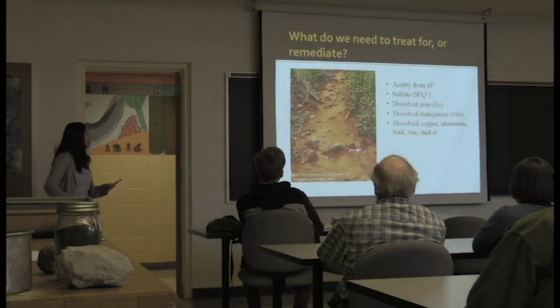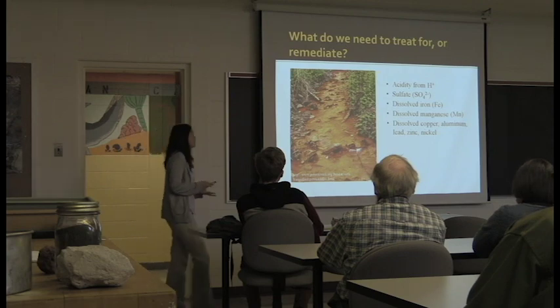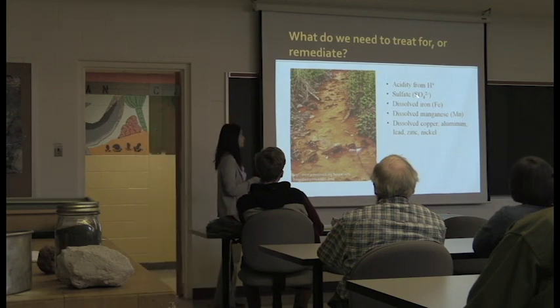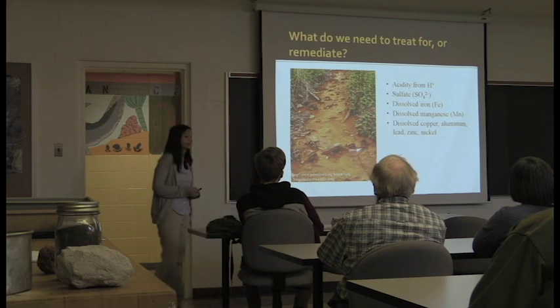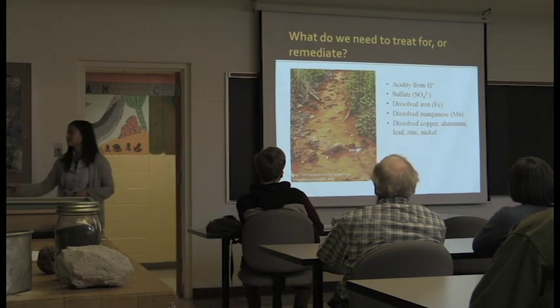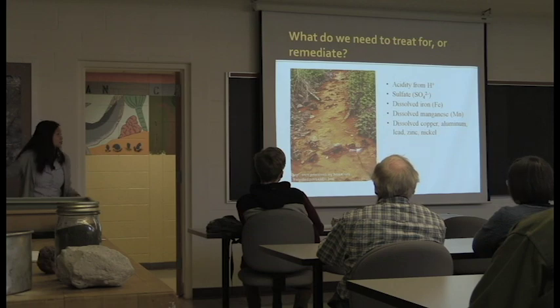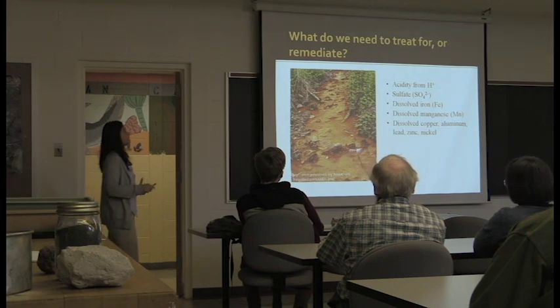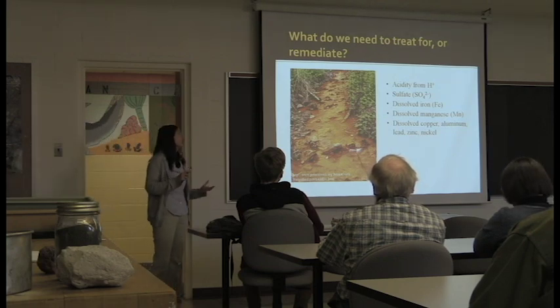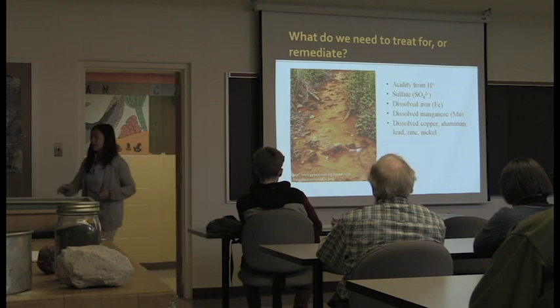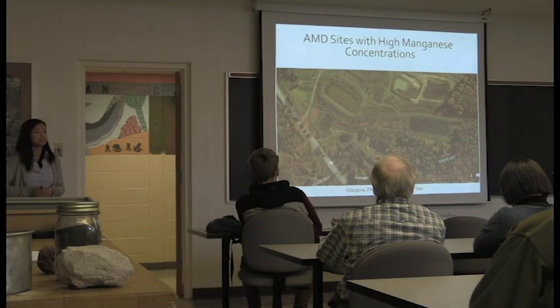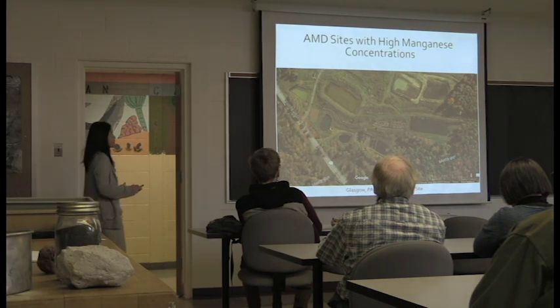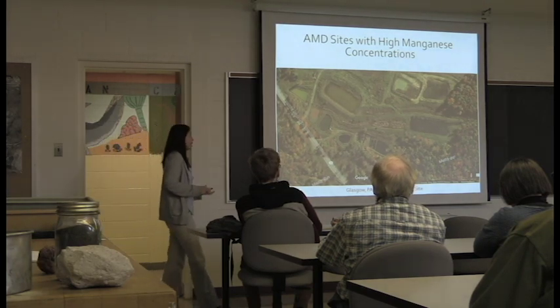So far, if we think about what we were trying to treat, we've treated a little bit for acidity, we've treated for sulfate, and we've treated for dissolved iron by letting it settle out as a metal oxide. Well, what about all these other things we have? We still have dissolved manganese, we still have dissolved copper, aluminum, lead, zinc, nickel, etc. The sites that I look at in particular tend to be these acid mine drainage sites that have a lot of manganese in them.